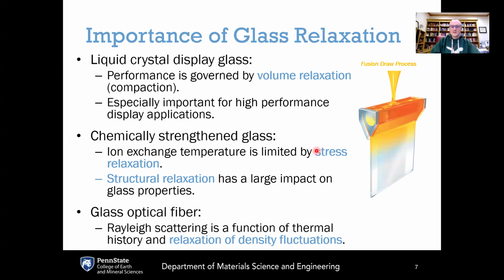And this relaxation behavior of glass and the flow of glass on long time scales, it's not just of interest for problems like determining whether or not cathedral glass flows. It's also critically important for many high-tech applications of glass. For example, these screens that you are looking at right now are made up of at least two pieces of very thin, highly engineered sheets of glass that have to be dimensionally stable during processing. And if the glass is flowing over time, that can lead to misalignment of the pixels. This is especially important for high resolution displays where the pixel sizes become smaller and smaller.